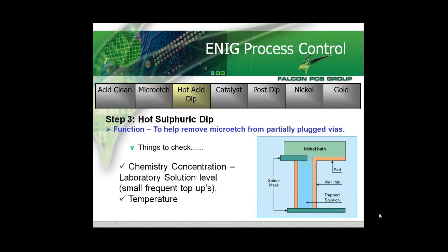Notice that we've all got the same slide, I think, just to demonstrate the problem with entrapped micro-etch solution. This is typical. Nigel explained it beautifully, and I'll leave it at that. Obviously, the copper ions in solution from the micro-etch cause the problems with the nickel.